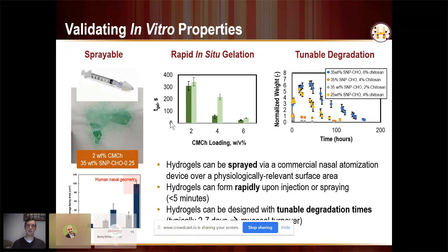We also can get tunable swelling and degradation, and in this case, between 2 to 7 days. And that's appropriate because it's very similar to the rate of mucosal turnover in the nose anyway. So beyond that, it's really not useful to have the material sticking around. And you'll see particularly the 35 weight percent SNP-CHO formulations with 2 and 4 weight percent chitosan, they didn't swell a lot, so we wouldn't anticipate it closing the nasal passage, but they also had the ability to stick around for that time period. So those are the ones we really focused on.